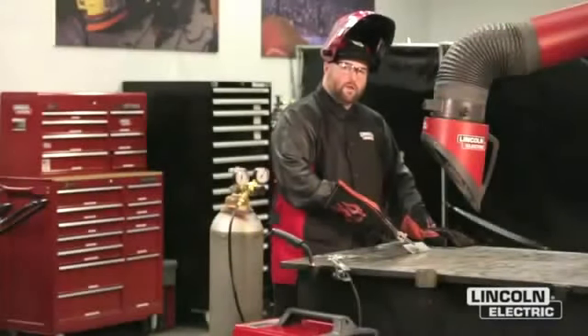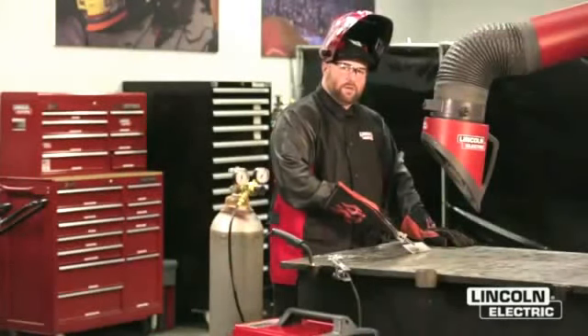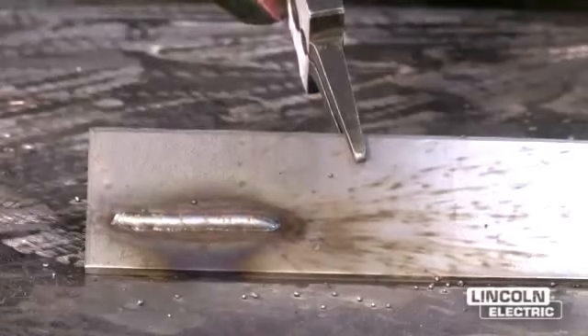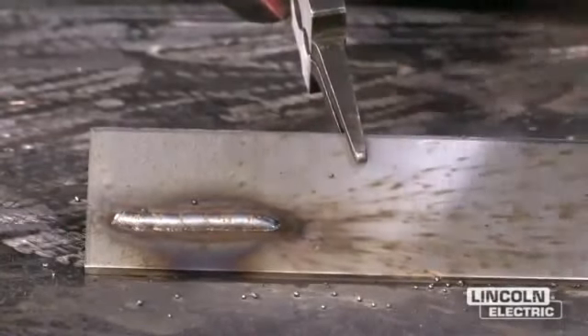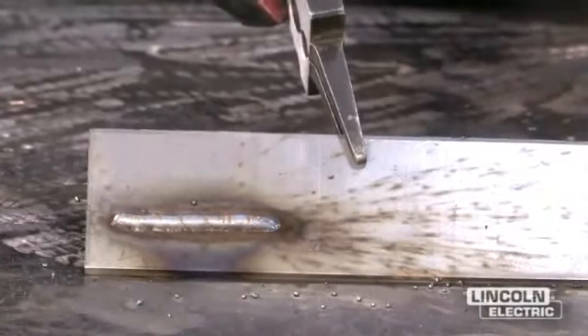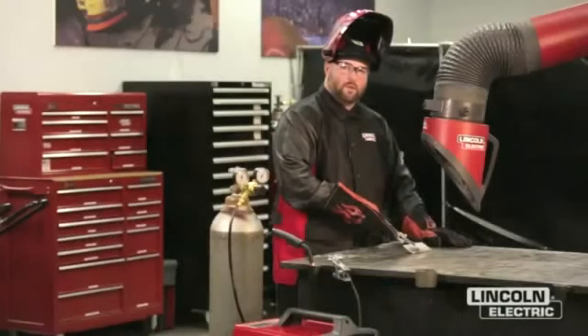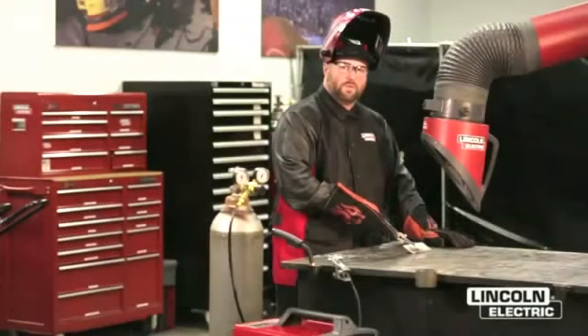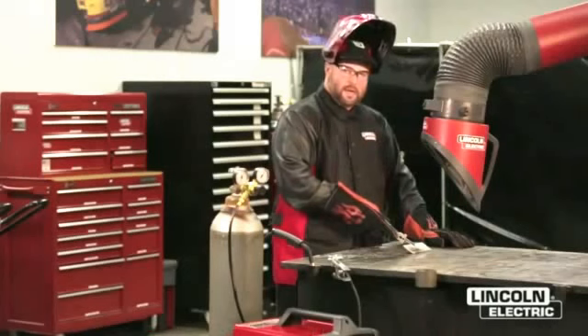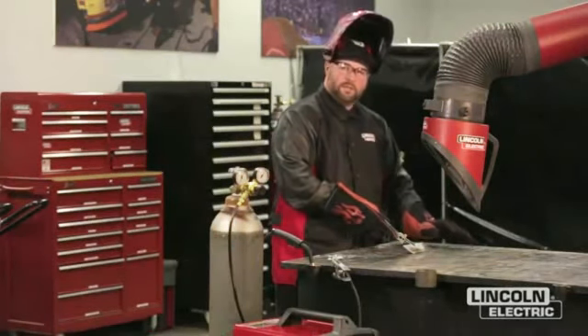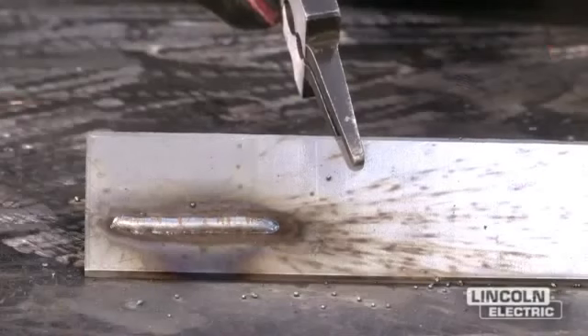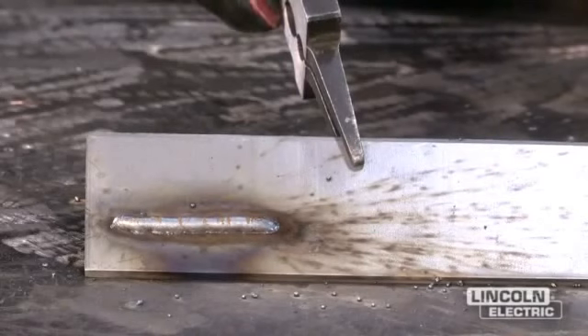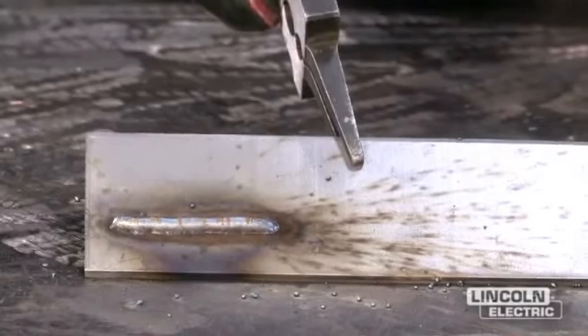So as you'll see, we just made a weld on DC negative with GMAW's short arc. And you can see the large amounts of spatter and a very inconsistent arc. So remember, make sure before you make a weld, especially if you're going back and forth between flux cord self-shielded and gas metal arc short arc, make sure you check the polarity first. Flux cord self-shielded on DC negative, gas metal arc short arc process on DC positive.